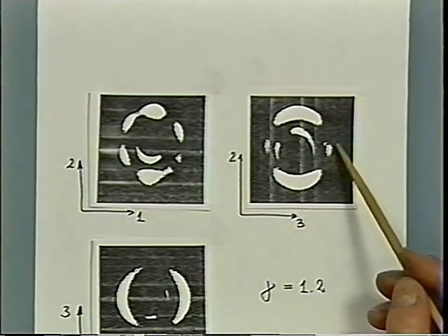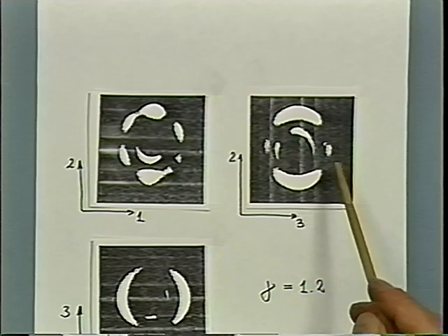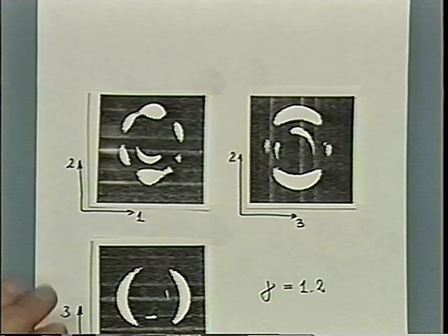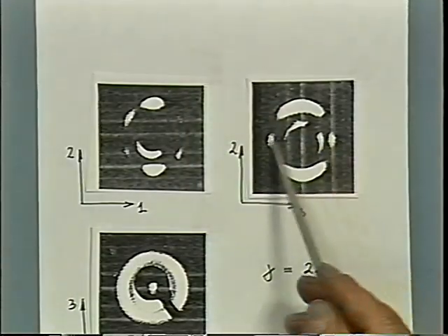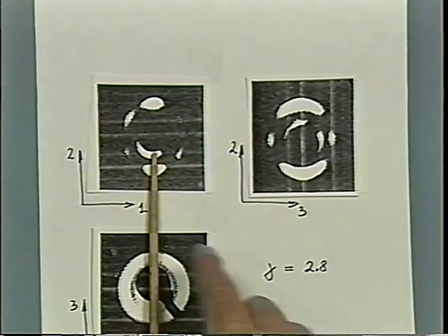Note that there's some intermediate structure coming in. So there's some regularity which gives us an additional reflection. The order wasn't perfect initially, so maybe some cylinders sticking out in their ordering very rapidly. And this intermediate order is even more drastic if we shear the sample by 2.8 shear units. The hexagons are still visible, not as strongly anymore. The intermediate structure is coming up here. And when this is from the side now, when looking on the top, you can see there's complete randomization.